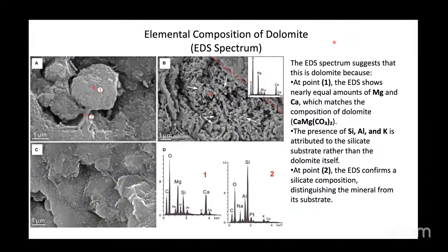Next one is the EDS spectrum, which gives us key insight into the composition of the sample, suggesting that the mineral is dolomite, and how we did this. Starting with point 1, the EDS spectrum shows nearly equal amounts of magnesium, you can see here, and calcium. This is a strong indication that the mineral is dolomite because its chemical formula is CaMg(CO3)2, meaning it contains equal amounts of calcium and magnesium. So, the presence of these two elements in similar proportion is a clear match for dolomite.